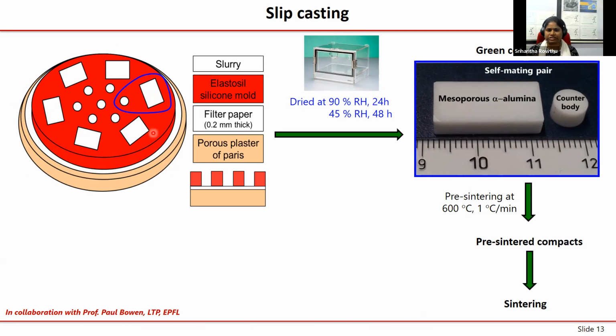If you don't know what silicone is, think of the phone covers you are using, right? That is essentially a silicone mold, silicone material. It's relatively elastic in nature, and this mold is open from the bottom as well as from the top. So now in these cuboids and also these cavities, we can pour the alumina slurry we have prepared, and let it dry.